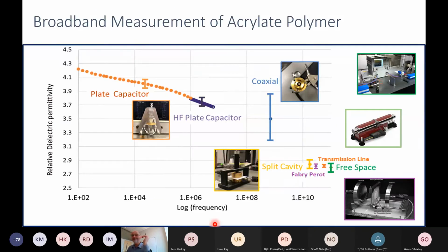So let's put it all together. Here we're looking at the relative permittivity versus frequency going from 100 hertz all the way up to 100 gigahertz shown here. And in general, we see this decrease in the relative permittivity as a function of frequency. So you can see here, split cavity, we had a Fabry-Perot technique. I didn't really cover that yet. And then we have transmission and free space. So those are all in here and they agree quite well.